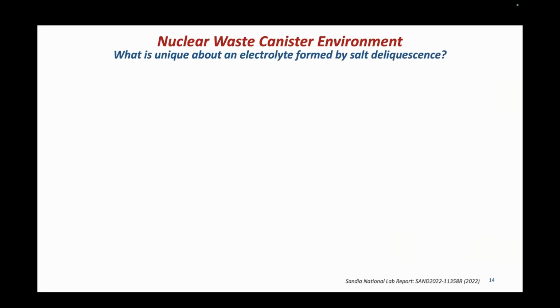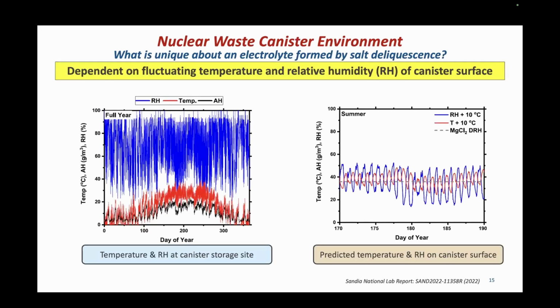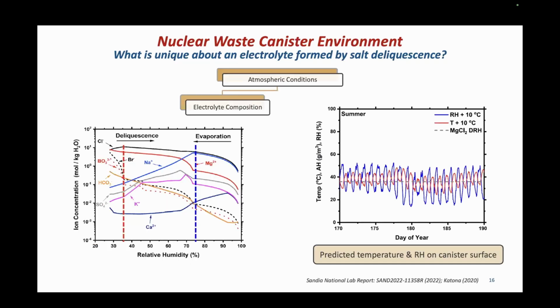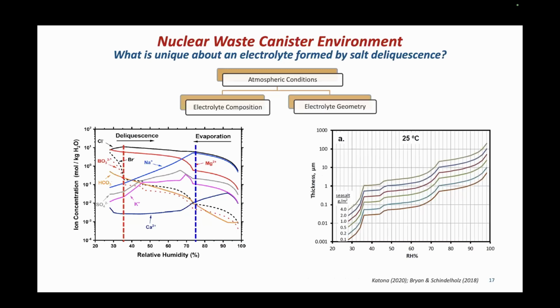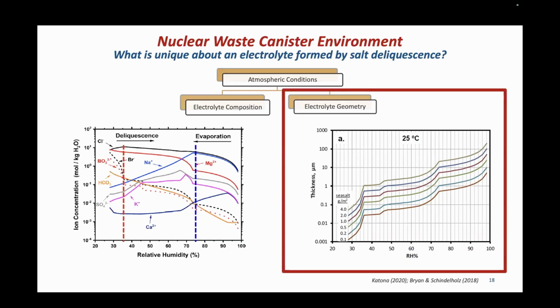So what would be unique compared to a full immersion testing about the electrolyte formed by salt deliquescence? The main thing is that it's going to be dependent on fluctuating temperature as well as relative humidity of that canister surface. And so eventually with time, we're going to start getting where that relative humidity is going to fluctuate quite a lot around that deliquescence of magnesium chloride, which is something that is found on those canisters. And when it comes to these fluctuations and just atmospheric conditions and deliquescence in general, it affects two main things. One is going to be that electrolyte composition. It's going to change the concentration of the solution on that canister surface, as well as electrolyte geometry, so that water layer thickness, and that's what we're going to be quickly looking at today.